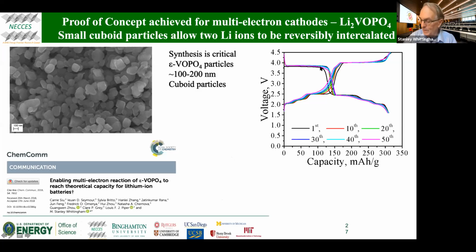And this is the electrochemical data we get out of this material. This is the vanadium 5, vanadium 4 redox plateau. Here's the 4 to 3. And you can see we get some ordering of the lithium ions in here. And it reproduces on the recharge. The important thing to note here, the first cycle is in black, the 50th cycle is in purple, and there's essentially no difference between these. So we got proof of concept that you can stuff two lithium ions into a crystalline lattice without destroying the crystallinity of that lattice. However, there are still some challenges with this material.